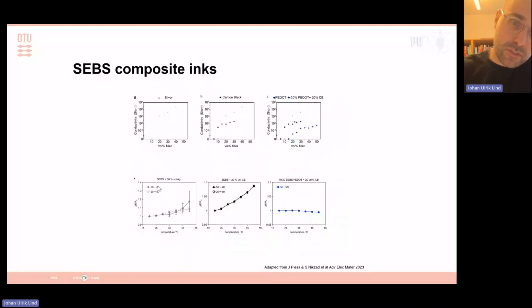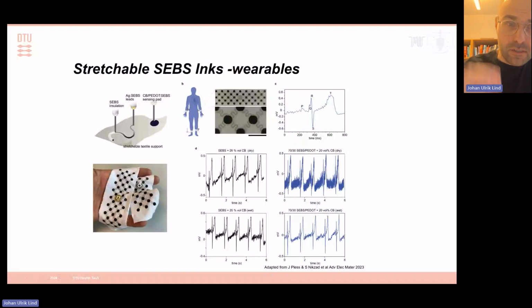So we studied the response to temperature sweeps of these systems. What we found was that our PEDOT system was very insensitive to temperature changes. So that's kind of interesting. And that our carbon black particle-based system was very nicely reversible in responses to temperature. So we are exploring that now for uses for wearable sensors. Here's another example of the same system being printed on top of textiles. We explore those as uses for real-time monitoring of ECGs of individuals through these printed electronics on textiles. And here's a couple of examples where we record that.